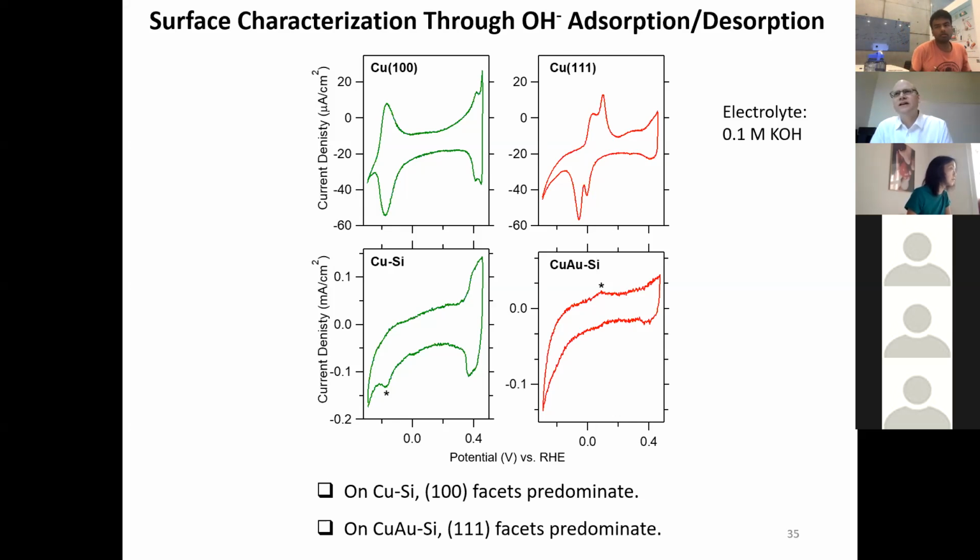Yes. So it's significantly more negative. I don't want to misspeak now, but I think in sodium perchlorate on polycrystalline copper electrodes, or also single crystal electrodes, the potential of zero charge is around -0.75 or so. So we're probably 0.4 volts or so more negative.